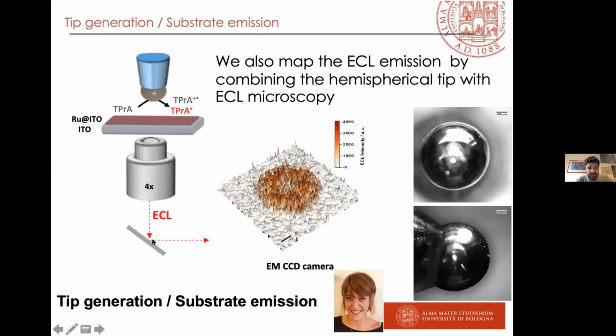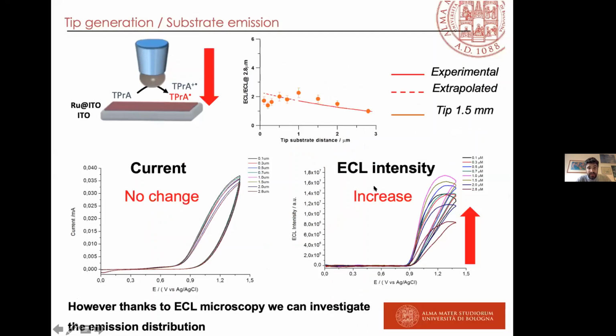a microscope. So we combine this emission with a microscope, and this is what we call ECL microscopy. This is our tip. And if you measure the current as a function of the distance, the current, of course, does not change too much, and you can measure the ECL intensity. And here you have an increase of the ECL intensity when you go closer to the electrode, to the ruthenium ITO layer.